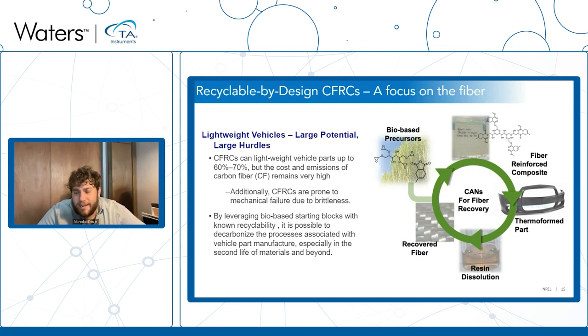So what we've said at NREL is, can we take bio-derived precursors, such as epoxies and anhydrides, and can we make an infusible resin, infuse it into glass or carbon fiber, make a part, and then thermoform that part using these kind of exchangeable networks that John mentioned in the previous talk, depolymerize the resin itself, and recover the fiber to actually enable circularity over multiple lives. And that's exactly what we've done.